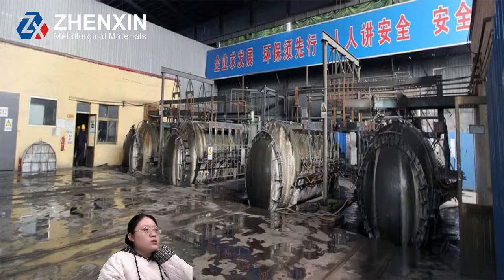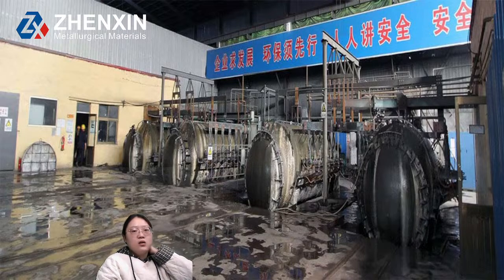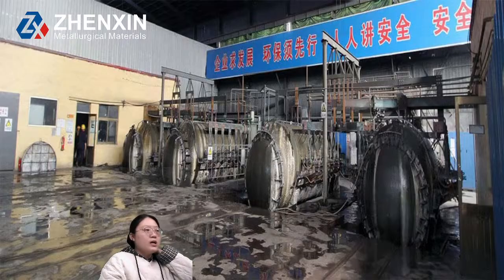And the second is the tundish cover method. The advantages are more controlled, higher recovery, and less violent reaction. The third method is in-mold treatment. Its advantage is that it is very precise, used for small batches and sensitive designs.